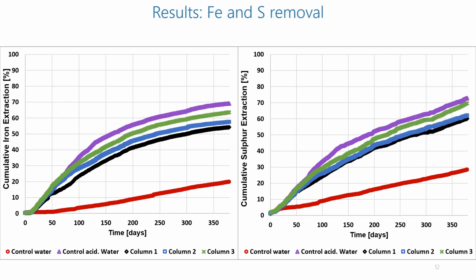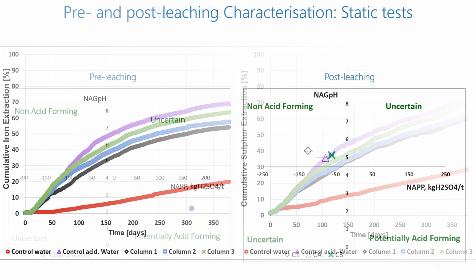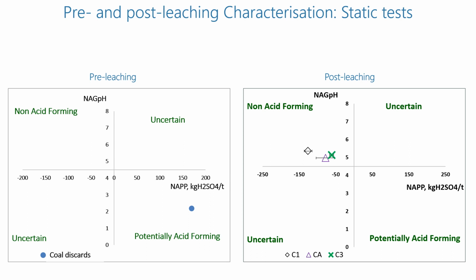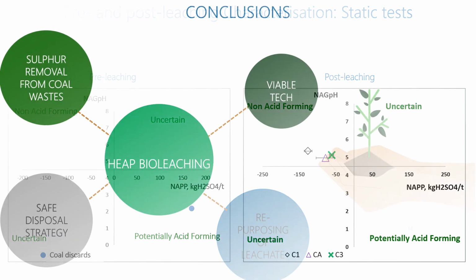Significant desulfurization was achieved in all columns irrigated with acidified water, with sulfur extraction reaching up to 70%. Post-leaching characterization has shown that the samples were non-acid forming.